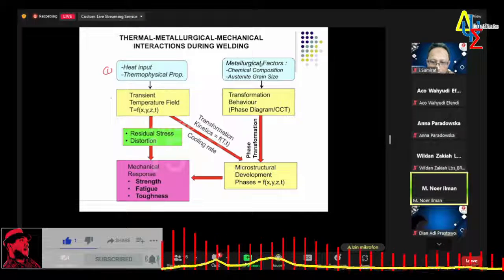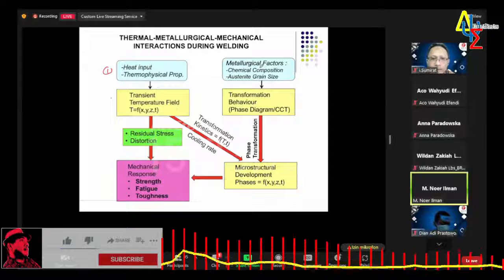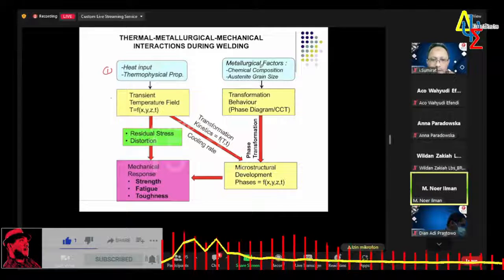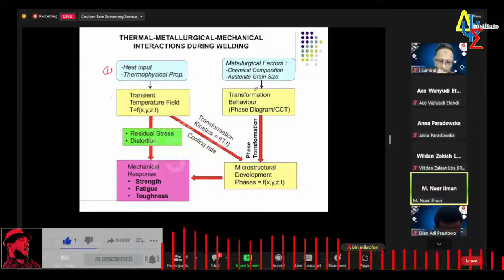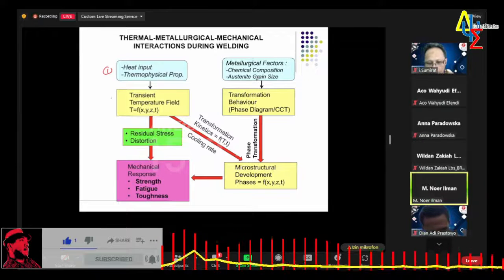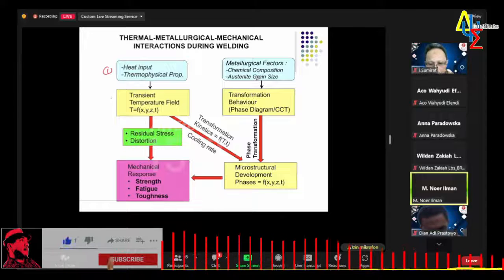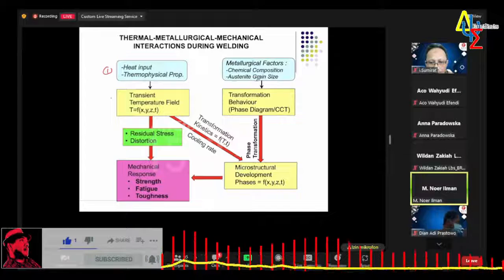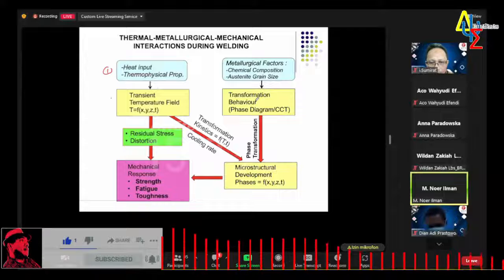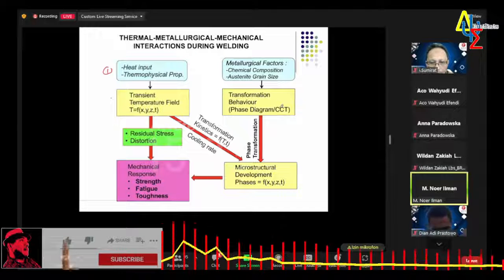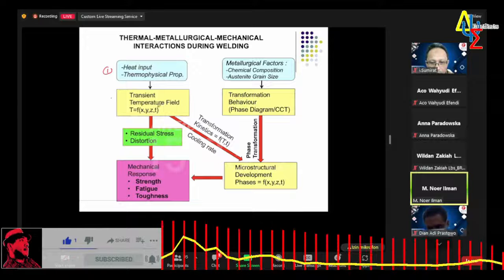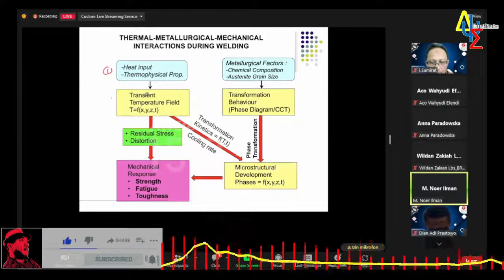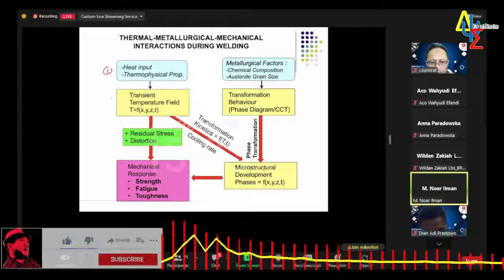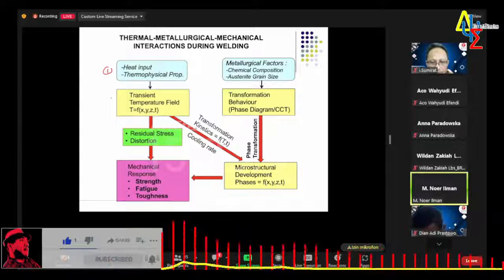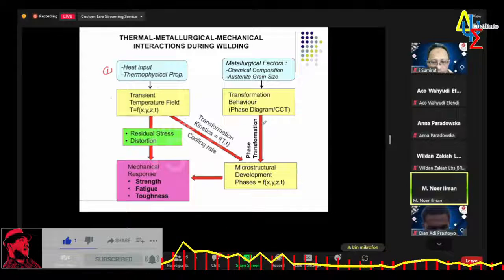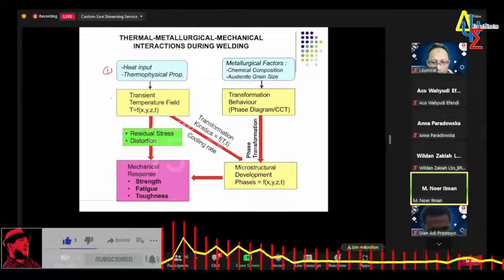On the other hand, the metallurgical factor plays an important role in affecting the final microstructure. We can see that metallurgical factors such as chemical composition and austenite grain size can affect transformation behavior, which can be seen from the phase diagram and continuous cooling transformation. And on the other hand, the heat input can influence cooling rate, so the combined effect between cooling rate and metallurgical factor produces the final microstructure.